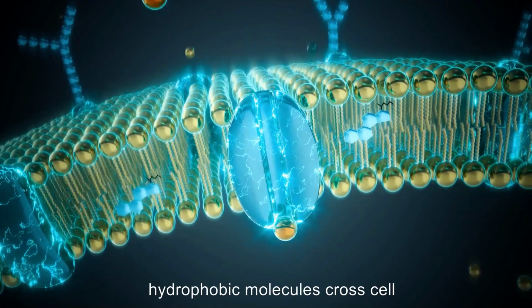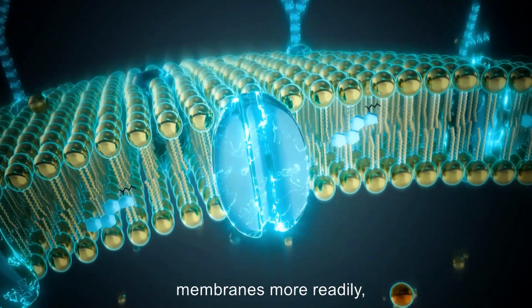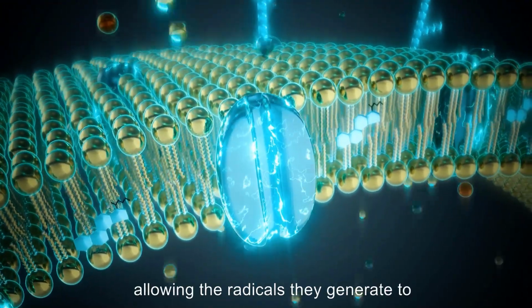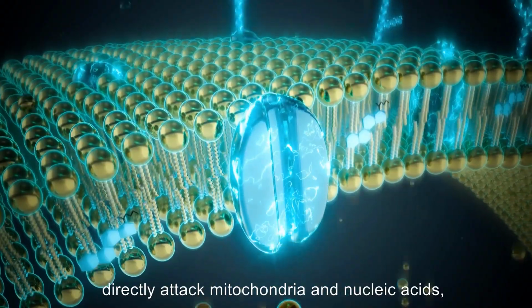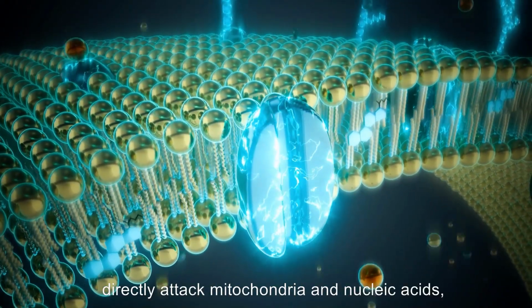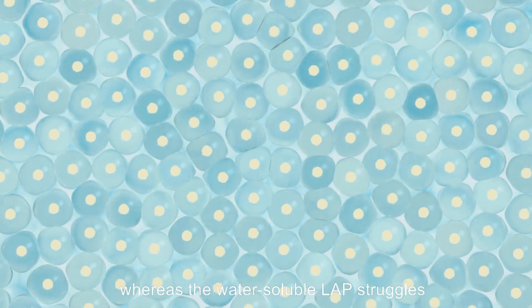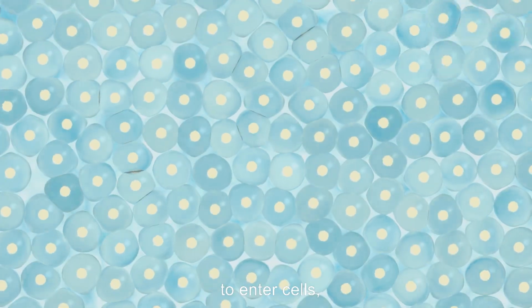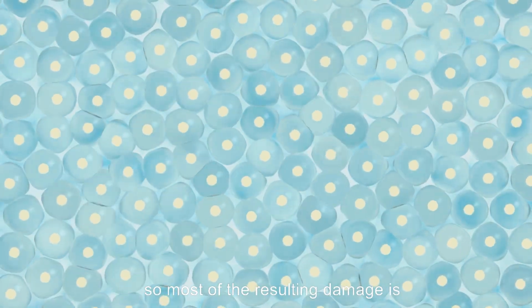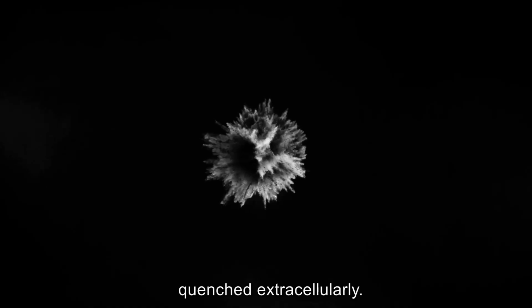More critically, hydrophobic molecules cross cell membranes more readily, allowing the radicals they generate to directly attack mitochondria and nucleic acids, whereas the water-soluble LAP struggles to enter cells, so most of the resulting damage is quenched extracellularly.